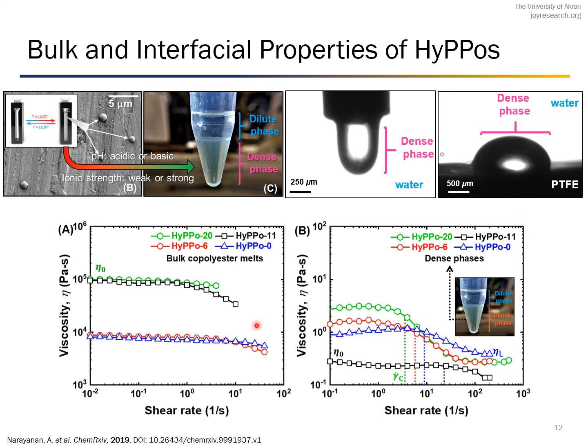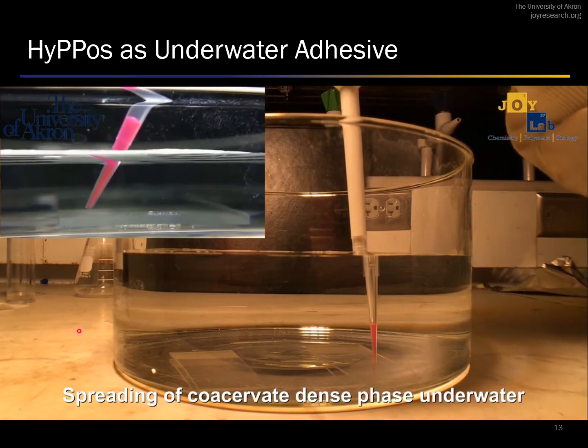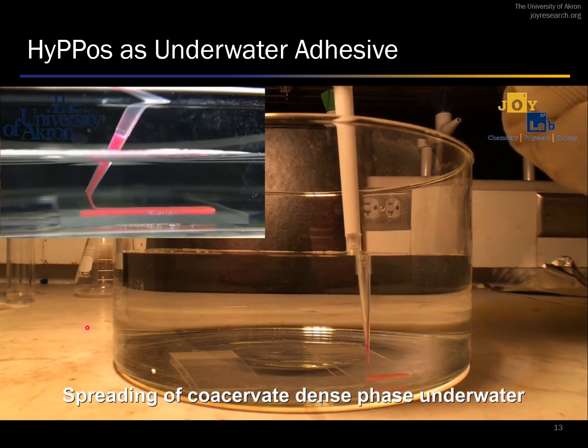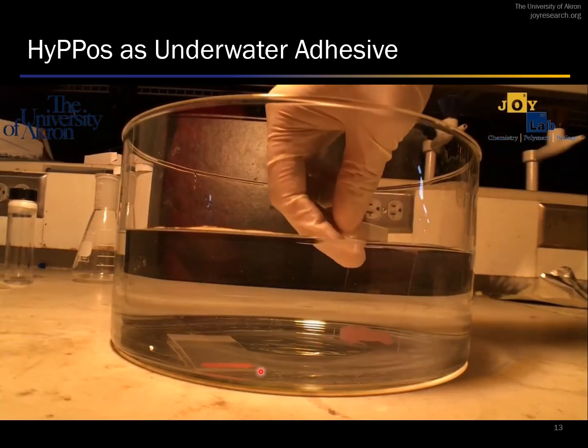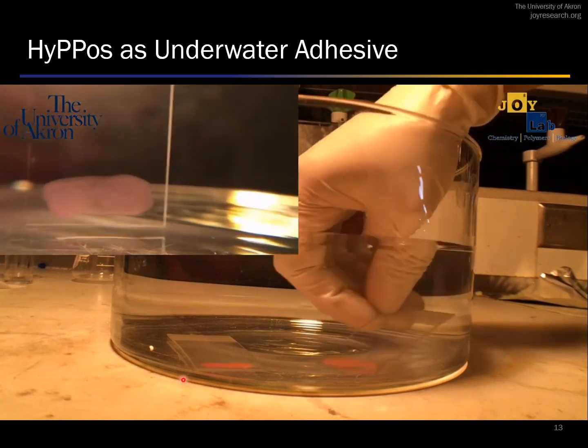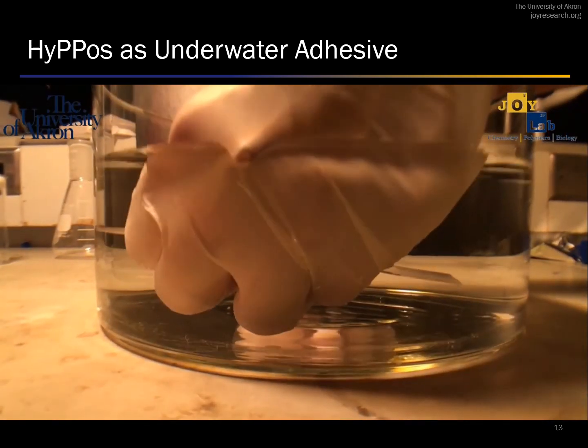Also, if you look at the viscosity of this material, the left side, which is the original polymer before it is dissolved, has high viscosity compared to the dense phase. And the dense phase also shows shear thinning behavior, which helps it to spread effectively in underwater conditions. As you can see from this video, the dense phase of these polymers is easy to spread in underwater conditions, and it adsorbs on the hydrophilic surfaces efficiently.